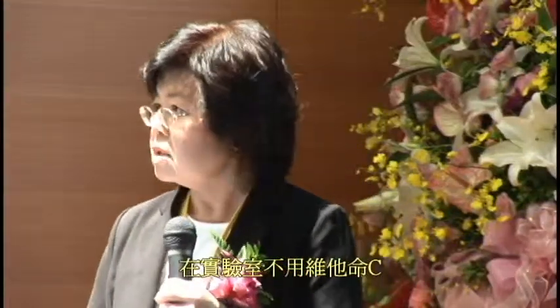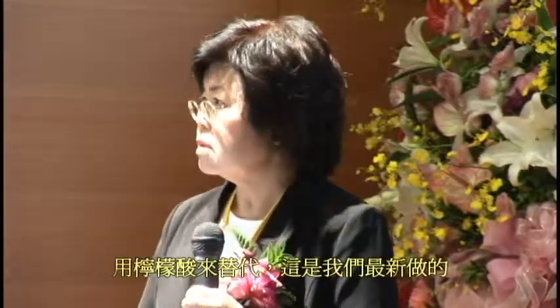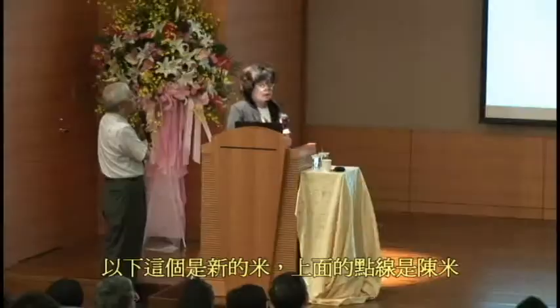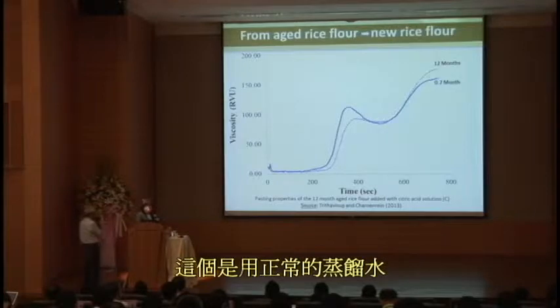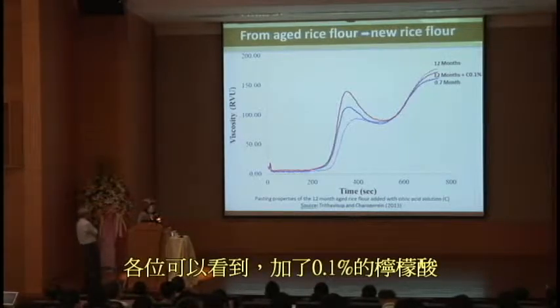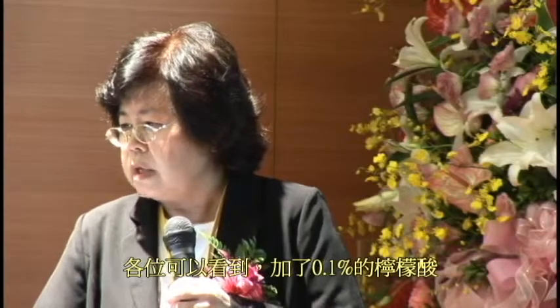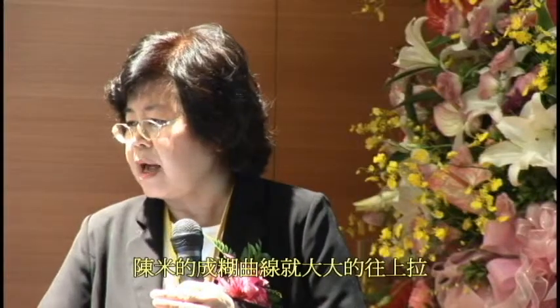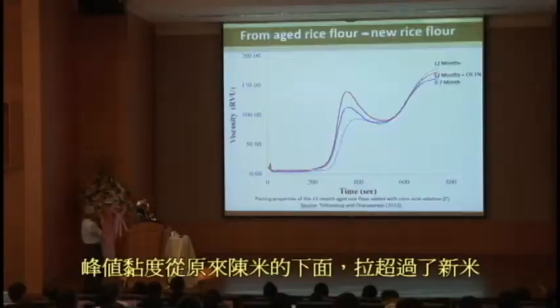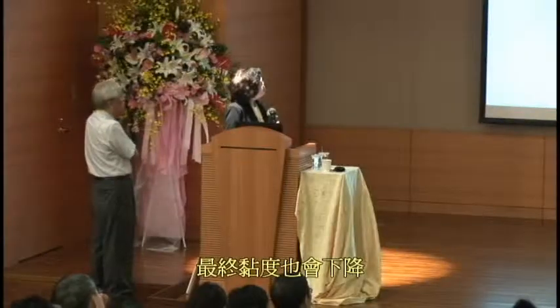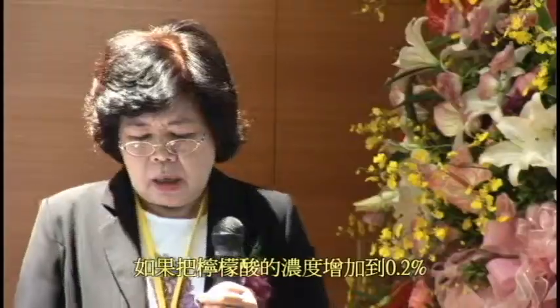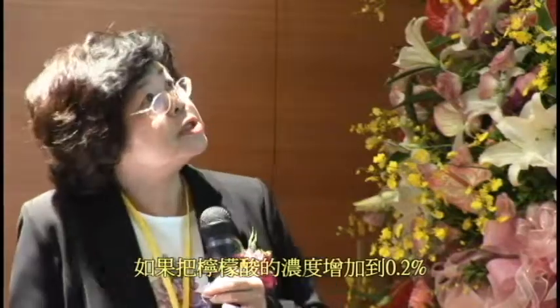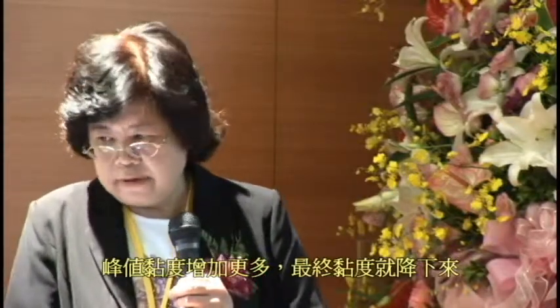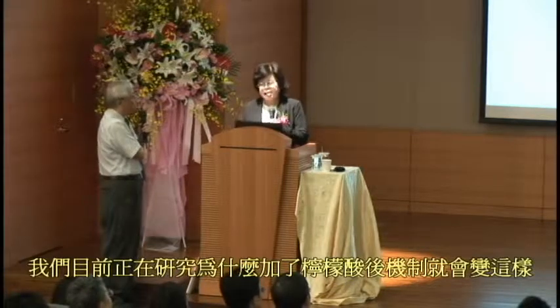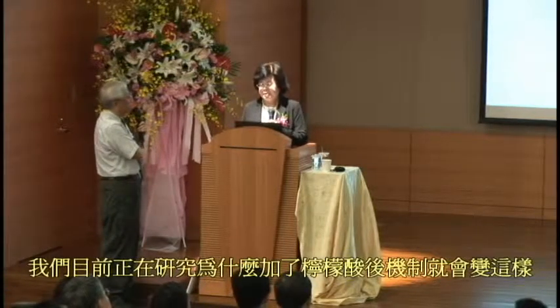The next one is the work in our laboratory. Instead of using ascorbic acid, we used citric acid. The dotted line is the aged rice with normal distilled water. When we ran the aged rice sample in 0.1% citric acid solution, we got the red profile. You can see that the peak viscosity increased from the dotted line to the red one, and also the final viscosity was reduced. And when we increased the concentration of the citric acid solution to 0.2%, we saw a more profound effect. We still need to figure out the mechanism of this, and my student is working on it right now.